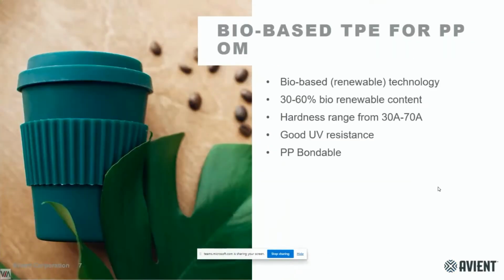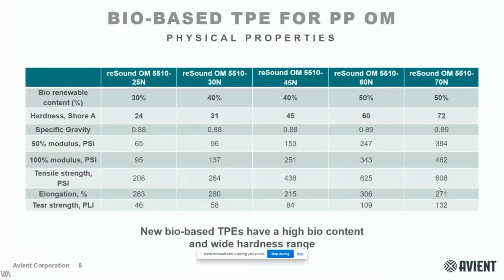Within this portfolio of bio-based TPEs, we achieve a high percentage of bio content, from 30 to 60% of bio-renewable content. Also a wide range of hardness, from 30 to 70, with good UV resistance and good adhesion to the PP base in case these products are overmolded. You see here the wide range of hardness and the basic parameters we can measure on these solutions. The hardness goes from 25 to 70, more or less, with quite good properties and a low density in the materials.